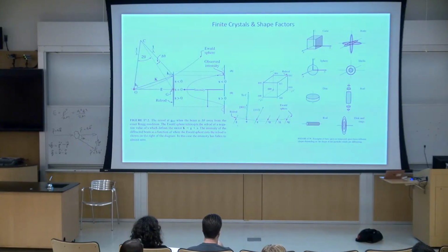We know when we Fourier transform this thing, I'm going to get a series of diffraction spots that, if this was spacing a, are going to be spacing 1 over a apart, an infinite series of spots. If I multiply the crystal by a shape factor like that, because it's a finite object, it's a nanoparticle, that means in the end I end up with just a whole bunch of dots there.